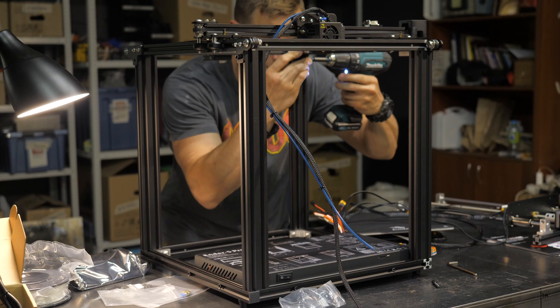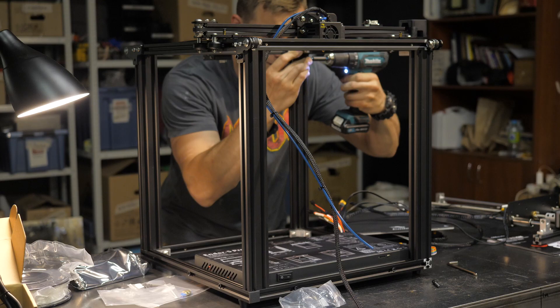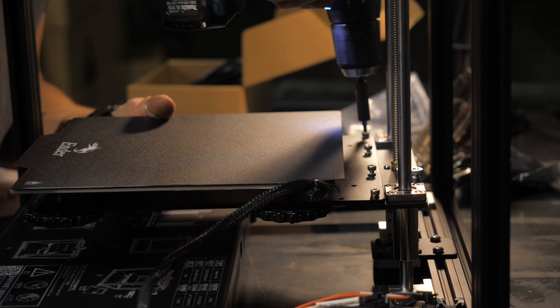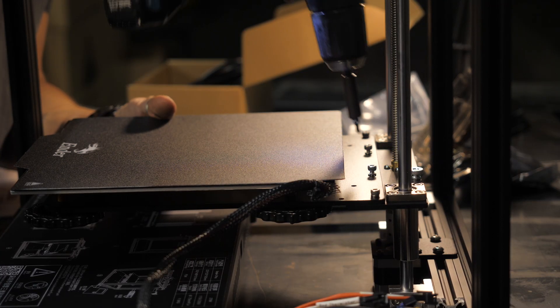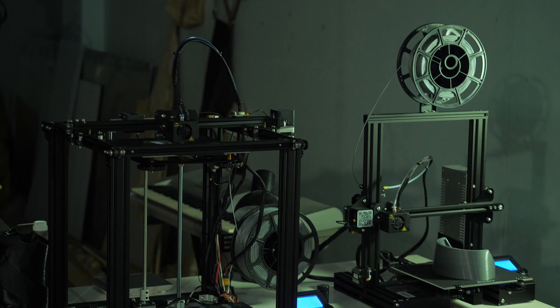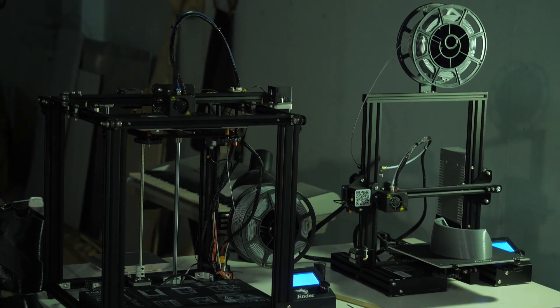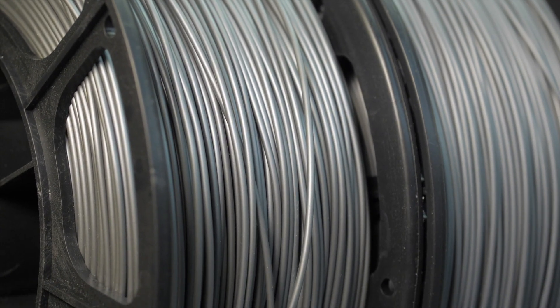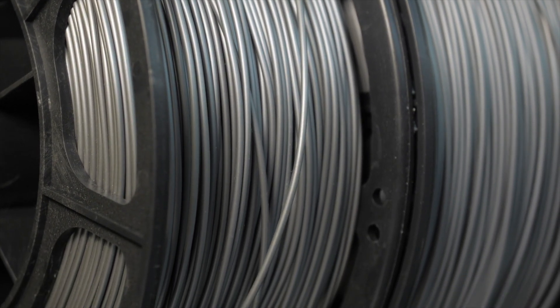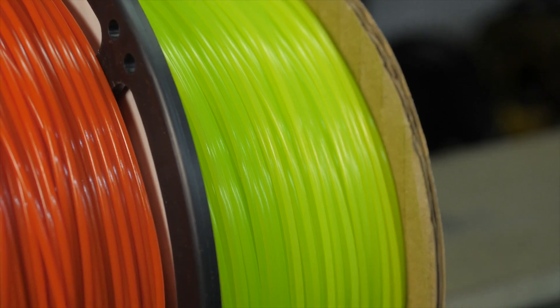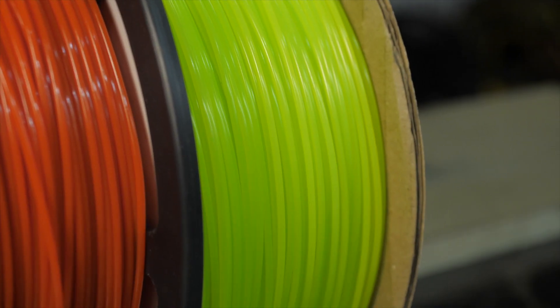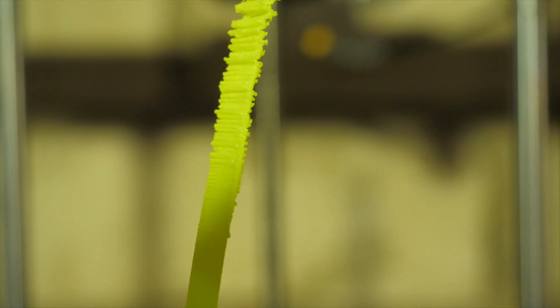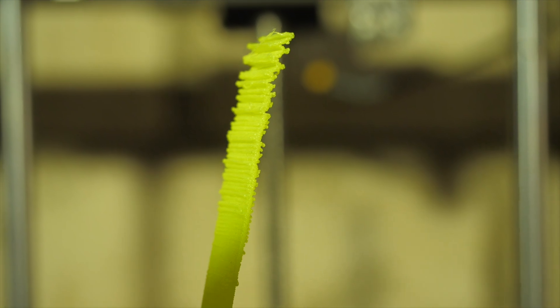Printers are best suited for printing such parts, in which the table doesn't move along the X and Y axis, but only down the Z axis. To print the matrix, it is better to use PLA or ABS plastic and do not use PETG, which creates print defects on the upper layers of high parts due to deformation during printing.